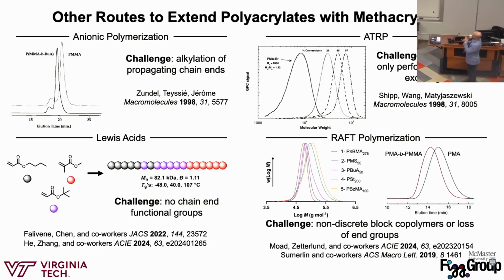So this was investigated over the years, but this is one example from 1998 where they're trying to make this block copolymer, and then we see that it's always bimodal when we make this. That means that we're not getting efficient chain extensions. And that's because the propagating anion with the methyl acrylate on the chain end isn't very sterically bulky, and it's actually getting alkylated by the monomer. So you're actually losing your anionic chain end because you just have monomer around and it's reacting on the ester of the monomer instead of propagating through. So you lose your chain end retention and you get this multimodal block copolymer trace. So anionically, you actually can't synthesize these sorts of acrylic, methacrylic block copolymers.